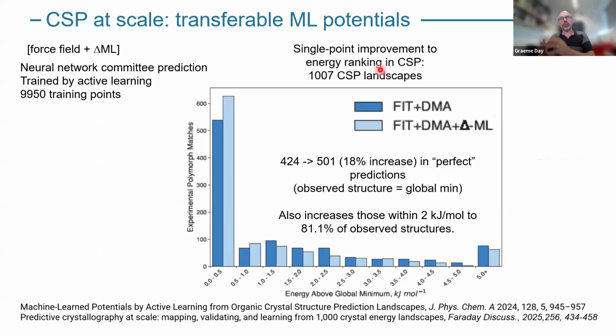If we then apply that correction to all of the crystal structures on all of our landscapes, then we can see that it improves the ranking. So these light blue bars are now after our machine learned correction. And now we've got almost a 20% increase in the number of perfect predictions we have, where the observed crystal structure matches up with the global energy minimum after this machine learned correction. We also get a reasonably good improvement in terms of the number of matches we find within 2 kilojoules per mole, which is that limit of where we expect to be when we're still ignoring vibrational contributions to free energy.